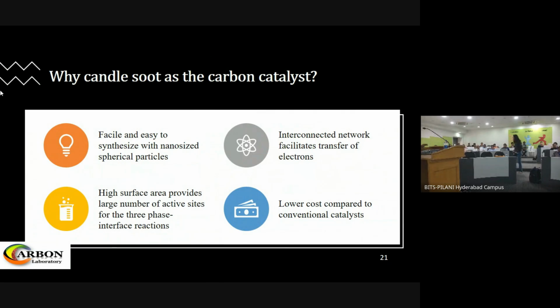So, of course, this is one of the most facile ways to synthesize carbon nanoparticles ever reported in the literature. You just light the candle and collect the soot. That is how you get the candle soot nanocarbon. The interconnected network of these carbon nanoparticles facilitates the transfer of electrons, which is good for energy storage devices or even on the catalytic side. High surface area again provides a large number of active sites, which is an essential condition for any catalyst, and of course lower cost compared to any conventional catalyst synthesis method.